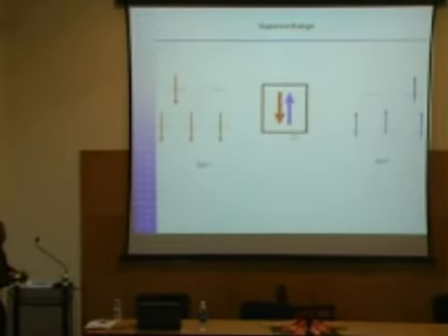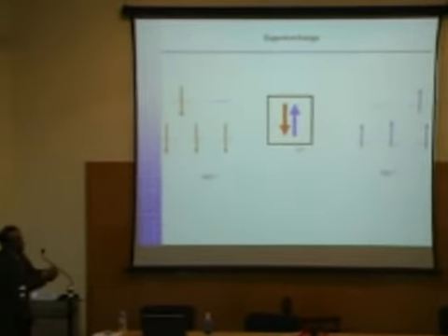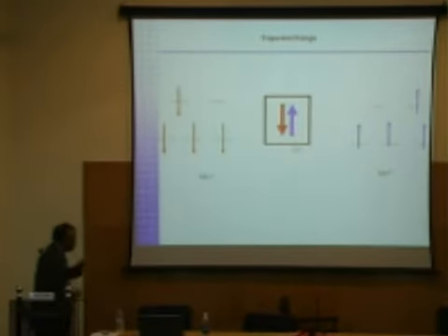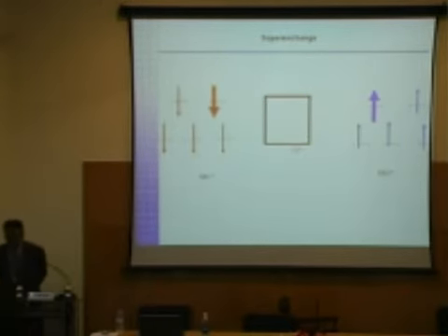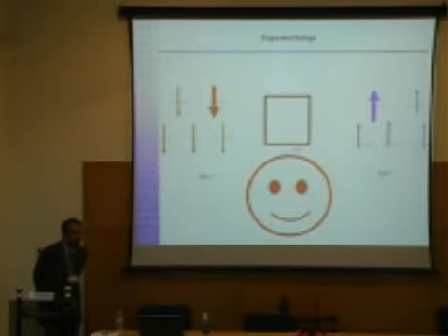Now what I have done here is I put one of the manganese spins down and the other manganese spins up. So the net moment of this manganese is pointing this way, and the net moment of that manganese is pointing that way. So clearly we're talking about an antiferromagnetic type of relationship. Let's see if that works here. Again, I'm going to transfer one of the electrons from oxygen, and you see I'm not violating any of the Hund's rules here. So as a result, whenever you have two manganese 3+ ions next to each other, the ordering generally tends to be antiferromagnetic, not ferromagnetic.